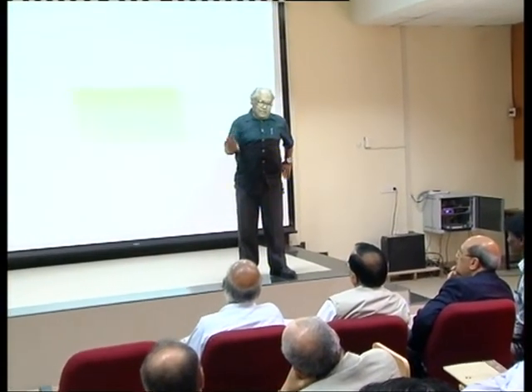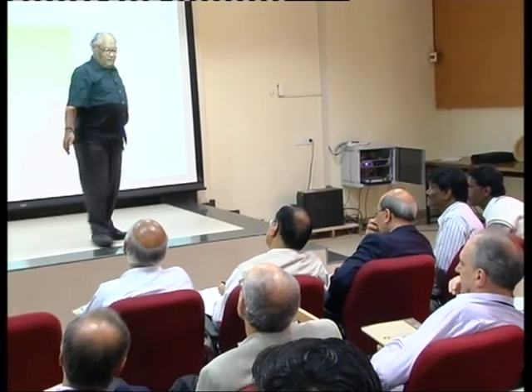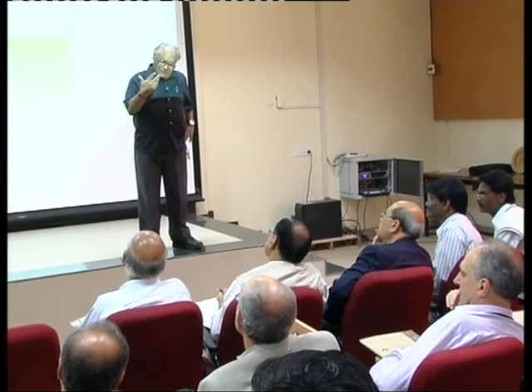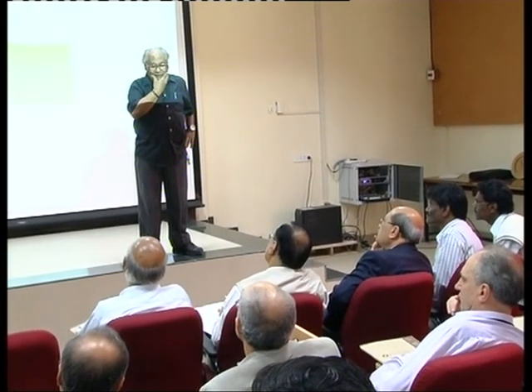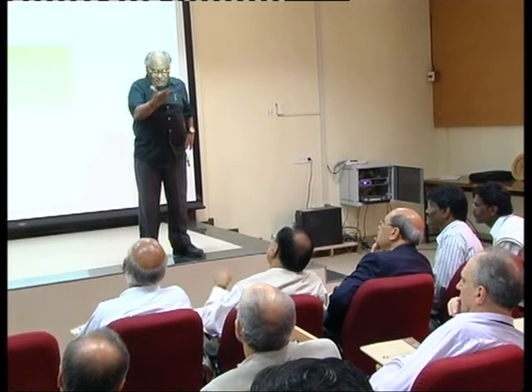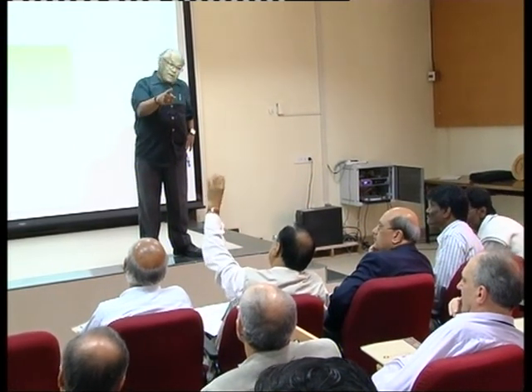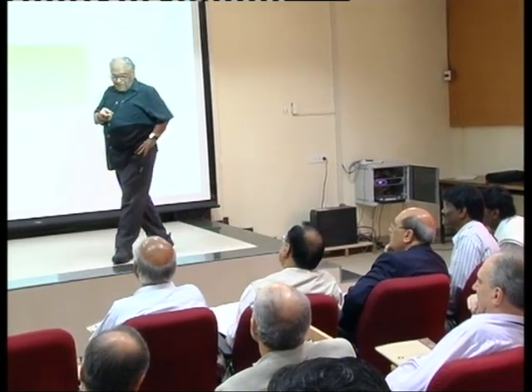Ferromagnetism is a difficult thing to happen, because in some of these materials, antiferromagnetism is much easier in all these ferrites. Very rarely do you get three-dimensional iron oxides which are ferromagnetic. Very rare. Most of them are antiferromagnetic. Same with chromium, same with manganese. So you don't have a ferromagnetic chromite or ferromagnetic manganite or ferrite. There is a spinel that is a ferrimagnet. The only aluminum ferrite I did was because it was a ferrimagnet, and I was able to bring it to room temperature. But it is not a ferromagnet. It is a ferrimagnet. Yeah, we can do some.